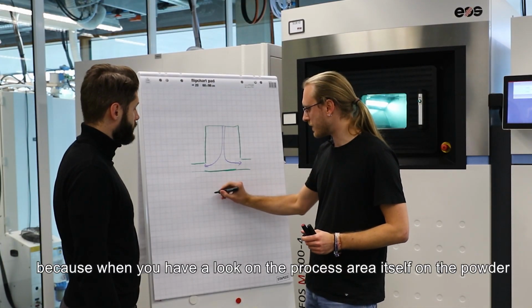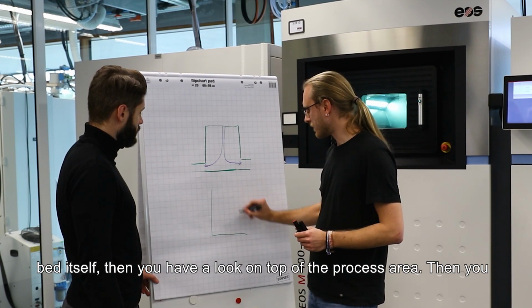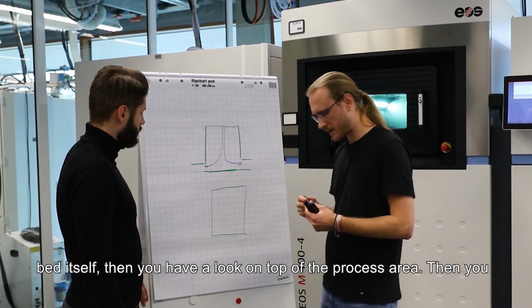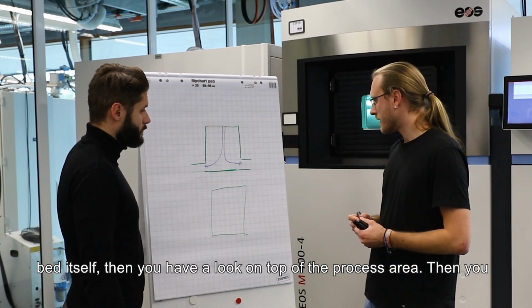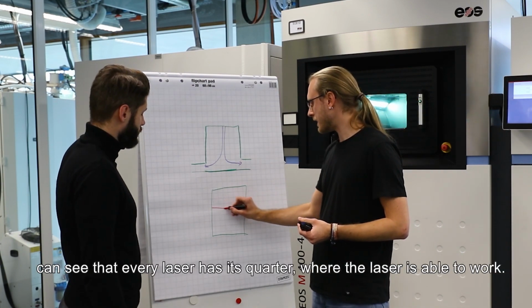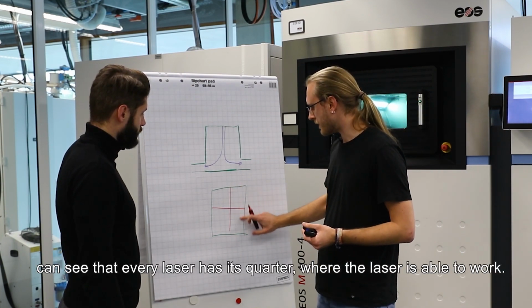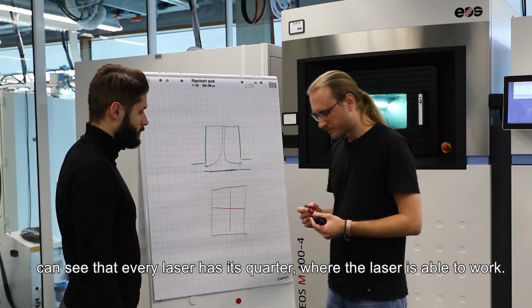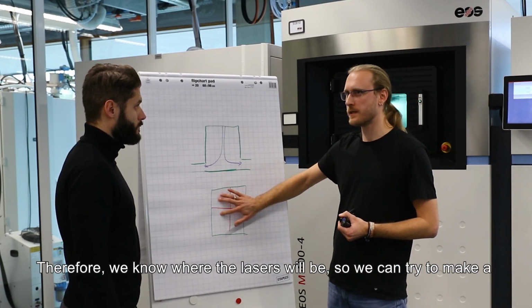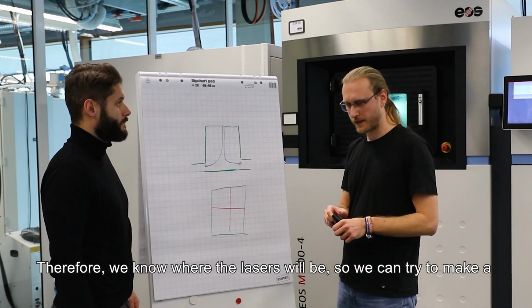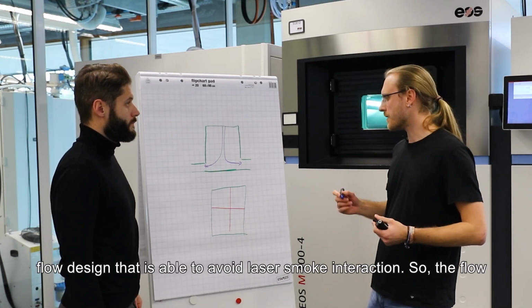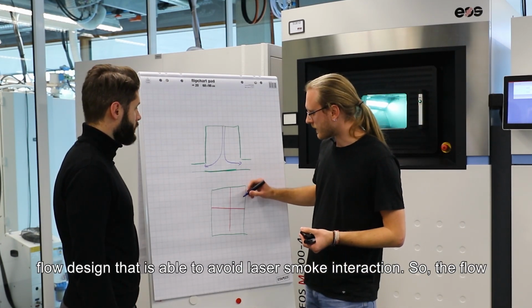We decided to use that flow concept because when you have a look on top of the process area, on the powder bed itself, you can see that every laser has its quarter where the laser is able to work. And therefore we know where the lasers will be, and therefore we can make a flow design that is able to avoid laser smoke interaction.